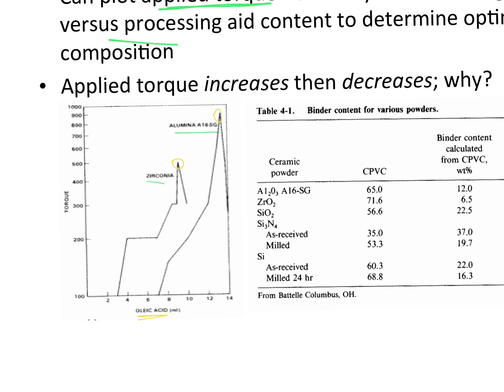Why is that? So this guy's doing the work of getting the particles away from each other, and beyond that, all right, it's not really necessary anymore. Some people say it's overdoing it, but anyway, the amount of energy necessary becomes less because the oleic acid is doing more of the work to tear things apart. So this is too little, too little, too little, and then we get to the right amount, and then beyond that, we have to do less torque to cause the same thing to happen, to rip these particles away from each other and introduce a layer that keeps them in the soft agglomerate state. Okay, and so this kind of outlines the balance between chemistry and mechanical force.